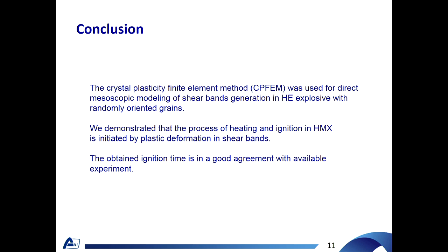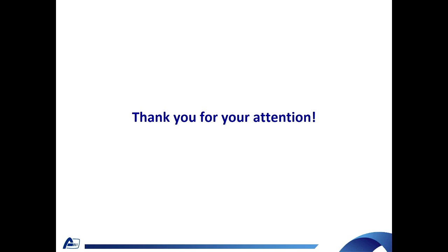In conclusion, the crystal plasticity finite element method was used for direct mesoscopic modeling of shear bands generation in HE explosive with randomly oriented grains. We demonstrated that the process of heating and ignition in HMX is initiated by plastic deformation in shear bands. And the obtained ignition time is in good agreement with the available experiment. Thank you for your attention.